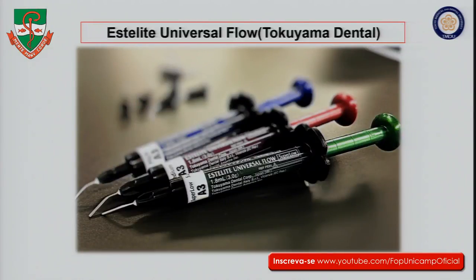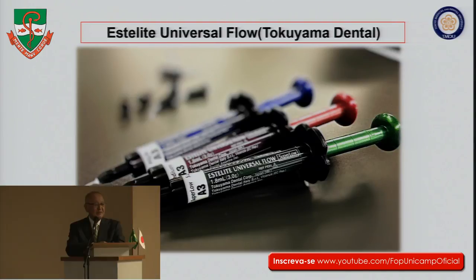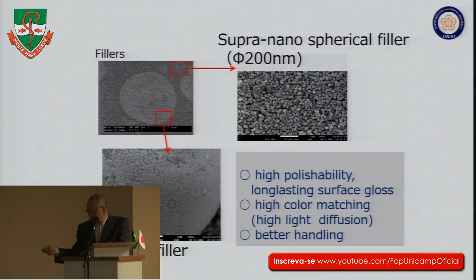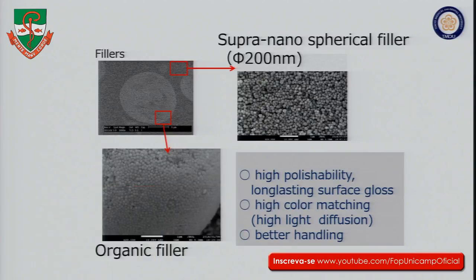But other kinds of adhesive composite resin materials were launched by many manufacturers. This is one of them. The Tokuyama company has a very unique technology of filler particles. They utilize spherical filler particles, and the size is 0.2 micrometers. Because of the size of this filler particle, the polishing ability is so excellent. With a very, very simple polishing technique, we can obtain a very excellent polish,